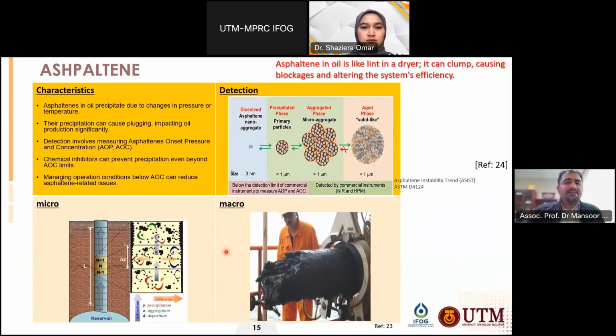This is a slide depicting the asphaltenes. What are the characteristics of asphaltene? Actually, asphaltene in oil precipitates due to the change in pressure or temperature. So the precipitates can cause plugging, impacting oil production significantly. Detecting involves measuring asphaltene onset pressure and concentration, so AOP and AOC. Then chemical inhibitors can prevent precipitation even beyond the asphaltene onset concentration limits. So managing operation conditions below AOC can reduce asphaltene-related issues.